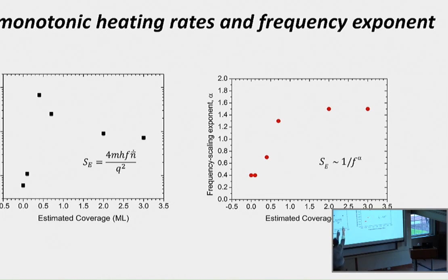The heating rate goes, this is where we started. It goes through the roof and then down to, there's your low heating rate, which is like 7 or something, quanta per second. And we have magnesium 25, and our trap is like 6, well, you saw what the distances were, but if there's no sample there, the ion height's about 60 microns.